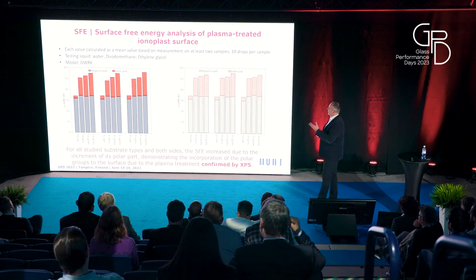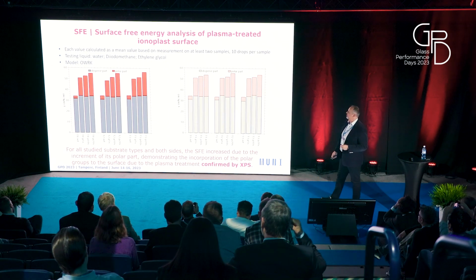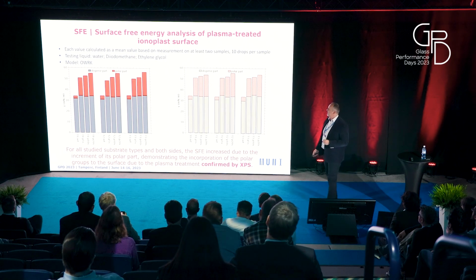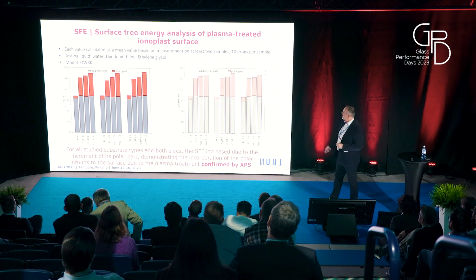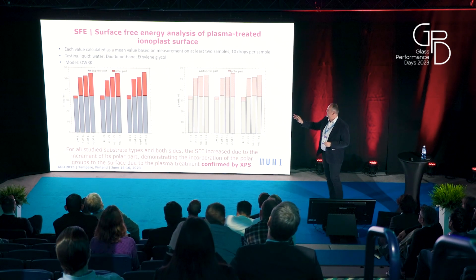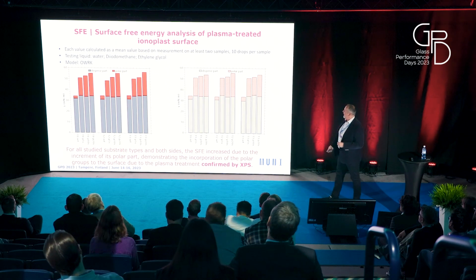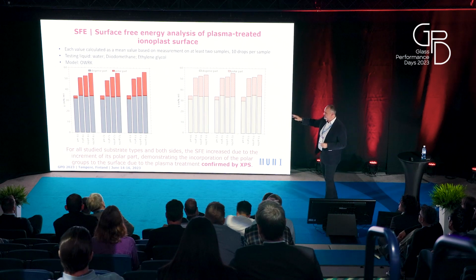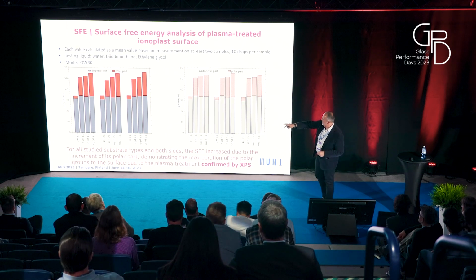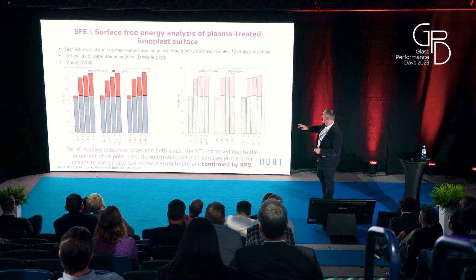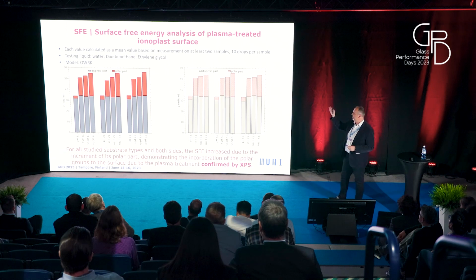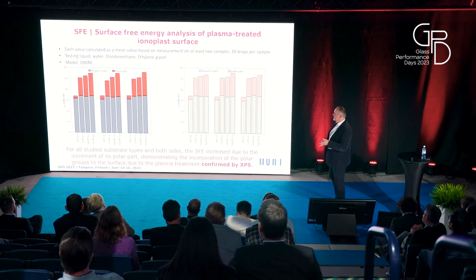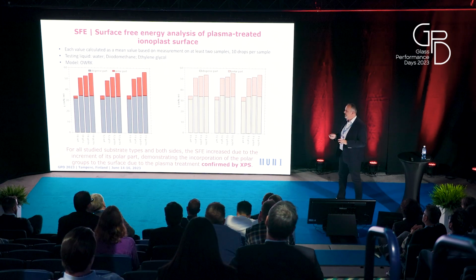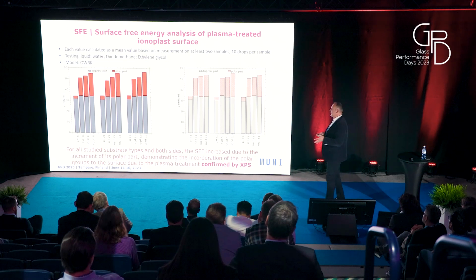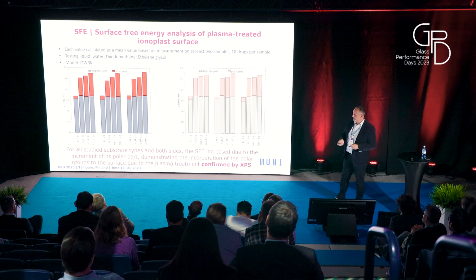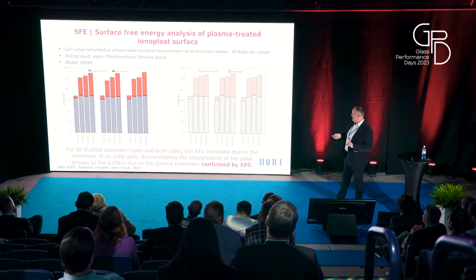We investigated also surface energy. In such a case, we were measuring water contact angle using more testing liquids, and we used the OWRK model for calculating. We investigated the smooth side of SentryGlas and the rough side on the right side. And as you can see, surface energy consists of a dispersive part and a polar part. For all plasma treatments with durations of 5, 10 and 20 seconds, we can see an increase of the polar part. So this is an indication that using the plasma treatment, we are incorporating oxygen content or polar groups into the surface, and we confirmed by XPS measurement, when we studied the chemical composition, that they are mainly oxygen-containing groups.